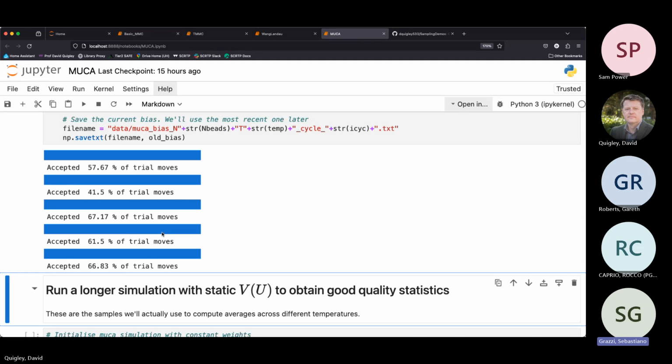You would never accept that in a million years. But with the multi-canonical sampling, you can say, I want flat sampling over some order parameter that distinguishes between the 2 minima in that augmented space. So I can get flat sampling, reweight it, and I can tell you at any hyperparameter what is the relative population of those 2 modes. There are definitely a lot of variations on the same theme, as you put it.